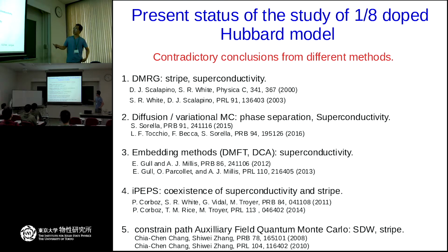Here is the present state of the study of the 1/8 doped Hubbard model with different methods. For the DMRG method, people find the stripe and sometimes find superconductivity. For diffusion and variational Monte Carlo, people sometimes find phase separation, and in other works, people find superconductivity. For embedding methods, for example DMFT and DCA, people usually find superconductivity in the 1/8 doped Hubbard model. For recent iPEPS work, people find the existence of superconductivity on a stripe. And for the constrained-path AFQMC method, which is the method I worked on, in our early work we found a spin density wave and a stripe. What I want to say here is that we have contradictory conclusions from different methods.